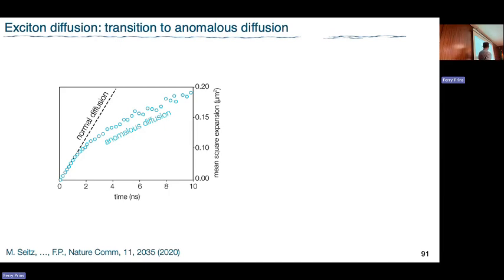So the point of inflection here is telling me about the trap density inside my material, because that's where I start slowing down. When I reach the traps, I get trapped for a bit, maybe move on, but things start slowing down. That's the trap density, and you can analyze that.